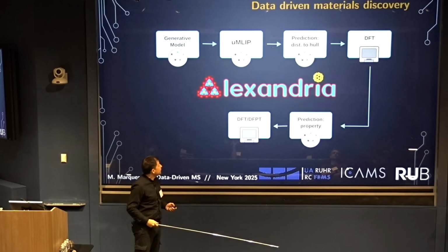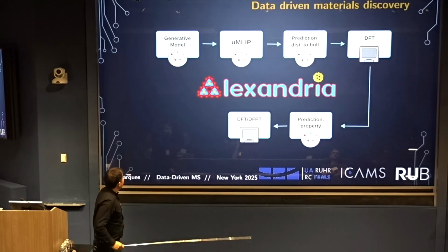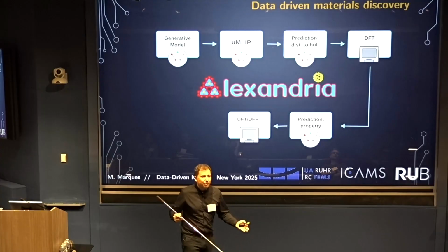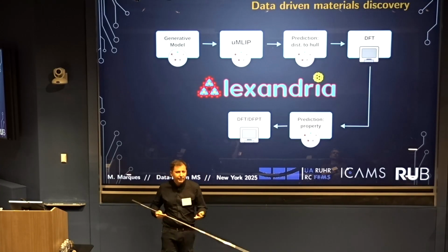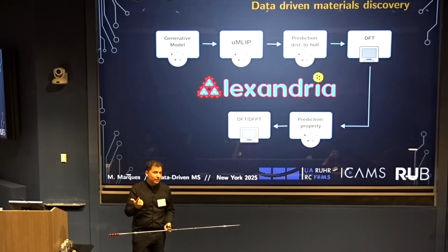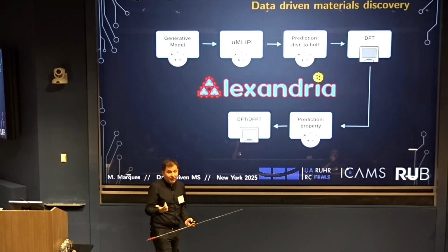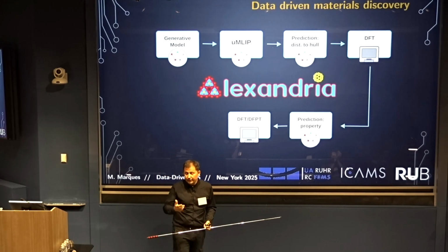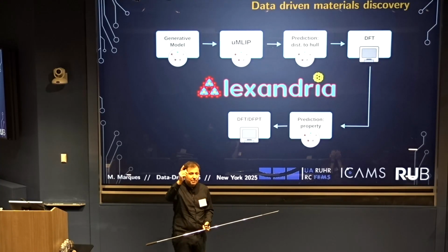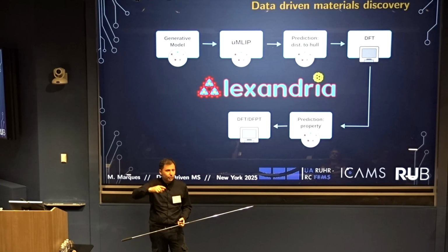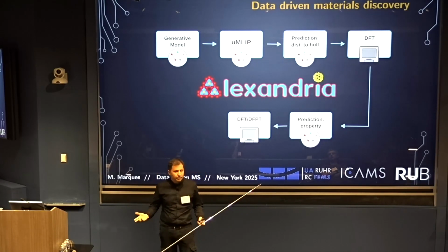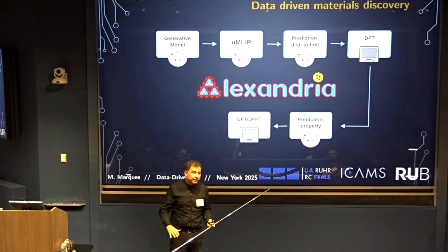So let's start. What do we do in practice? Well, we need to start our loop. We need example materials. So we need something that suggests compounds to us. Compounds means a crystal structure and the chemical composition, of course. Sometimes we just grab a crystal structure, that can come from wherever, and then we systematically change the chemical composition through the entire periodic table. For example, for a ternary compound, this gives 500,000 possibilities. 500,000 is not so bad.